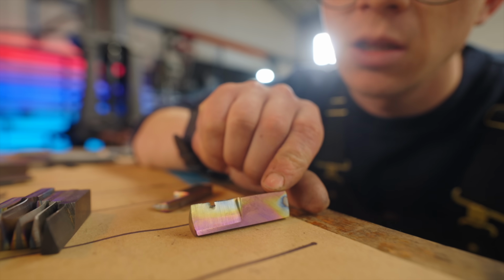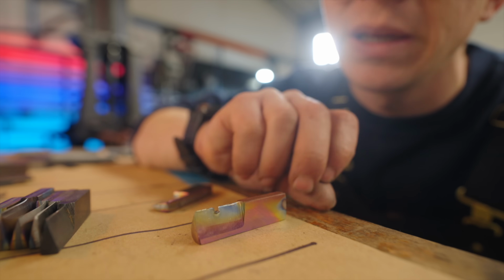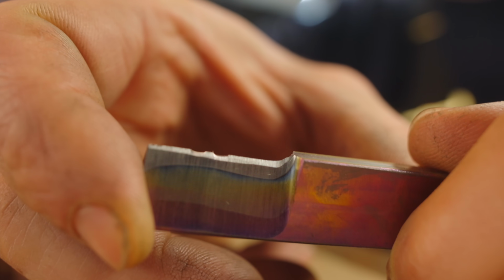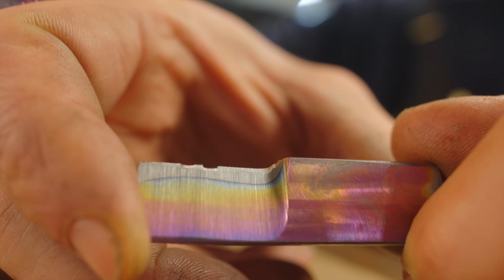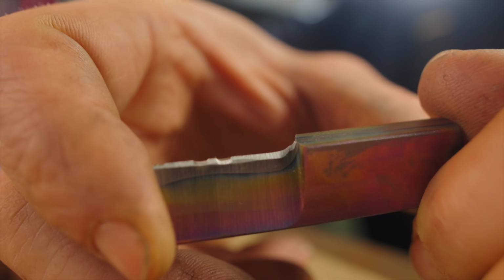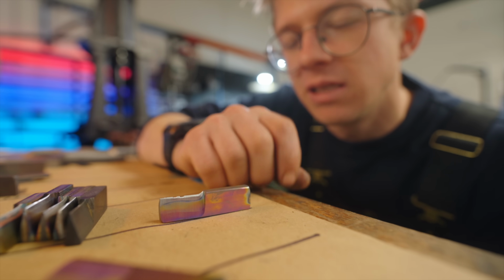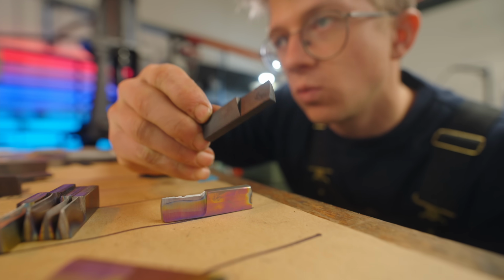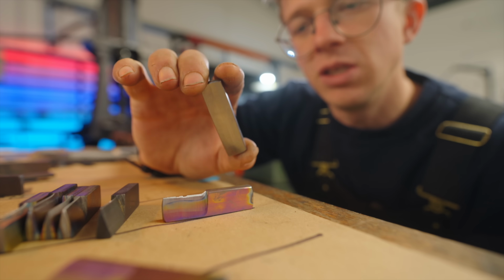However, it was no surprise that the titanium control failed miserably, but it was a surprise to have the edge roll on our direct bond sample number 10, and that was very disappointing. Now, something I'm considering here is this. All of these samples were quenched when they were at this dimension.